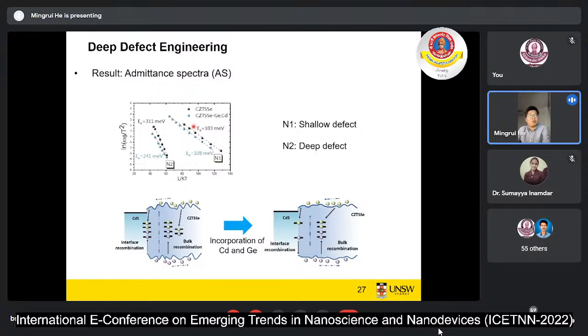But fortunately, after alloying the cadmium and doping the germanium, the defect levels have been reduced a lot. Here I plot some figures. Without doping, we have many different deep defect levels that can act as recombination centers that limit the efficiency. After that, the deep defect levels were reduced, so we got less recombination in these films, which shows a higher performance.